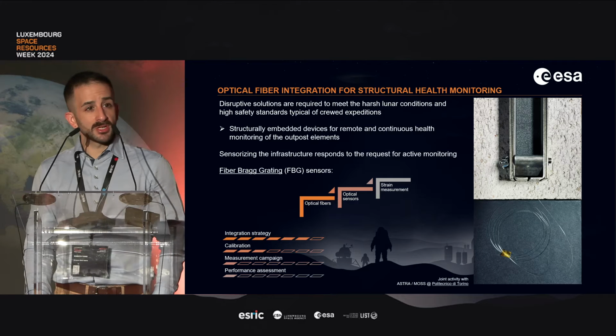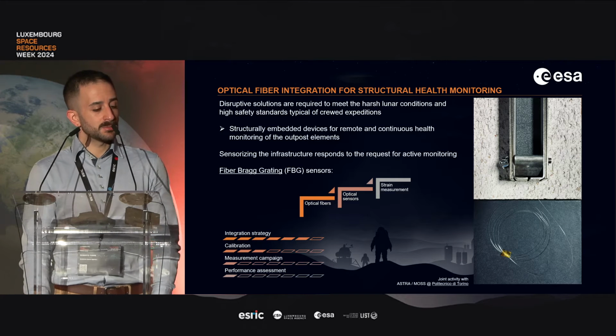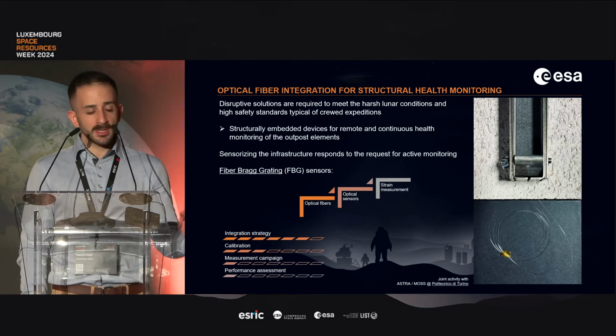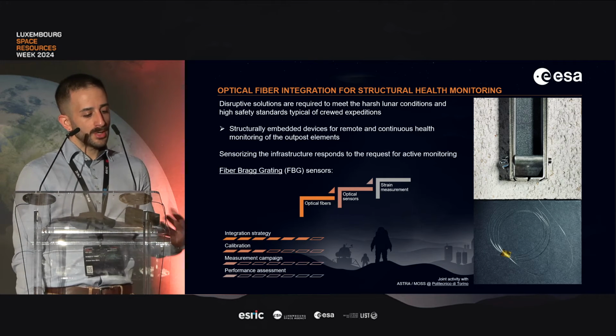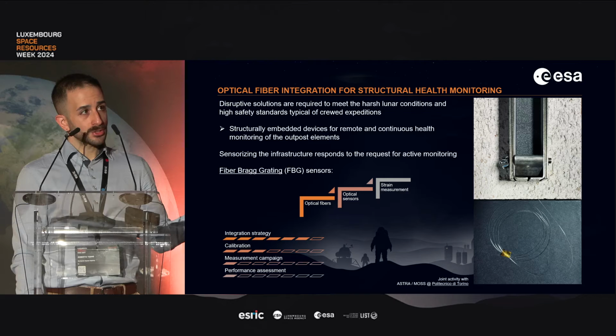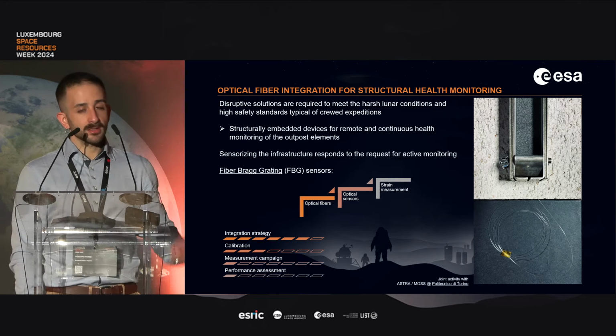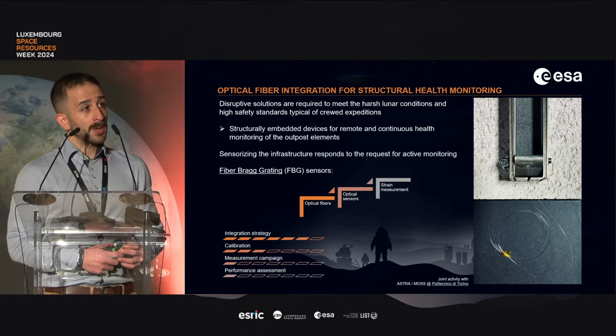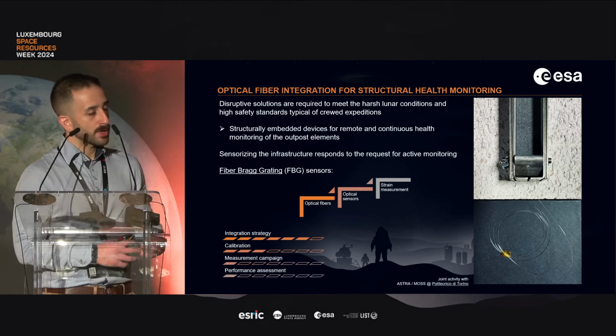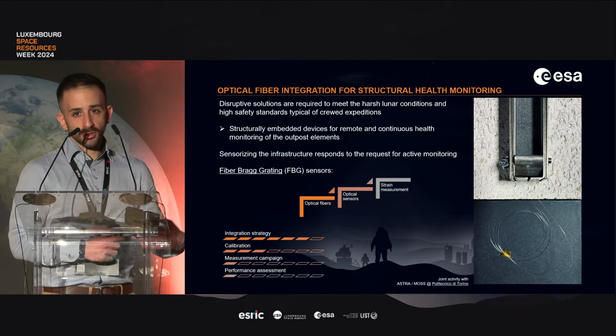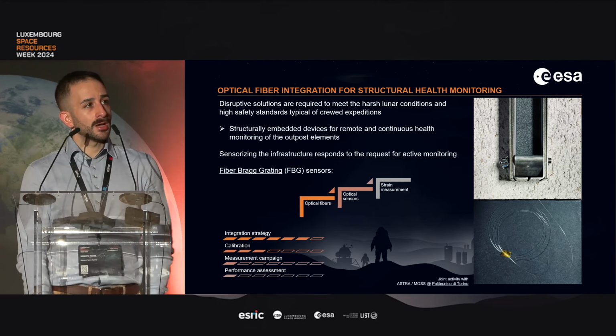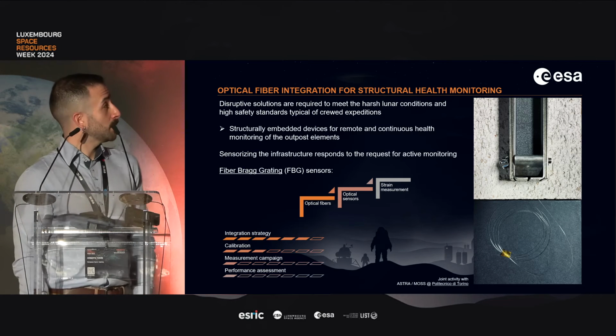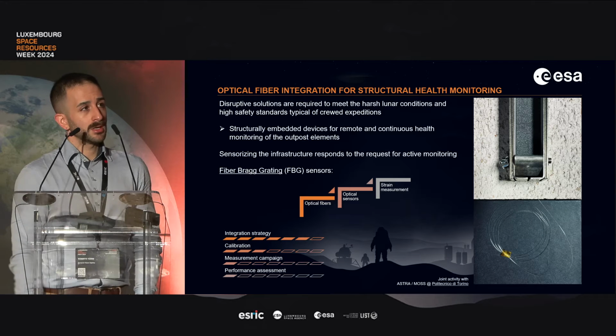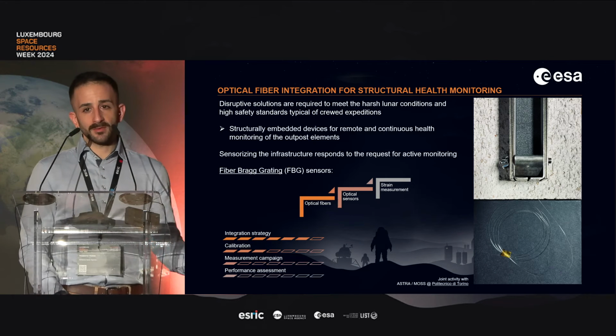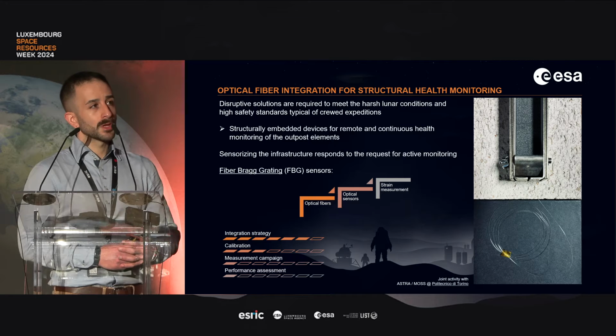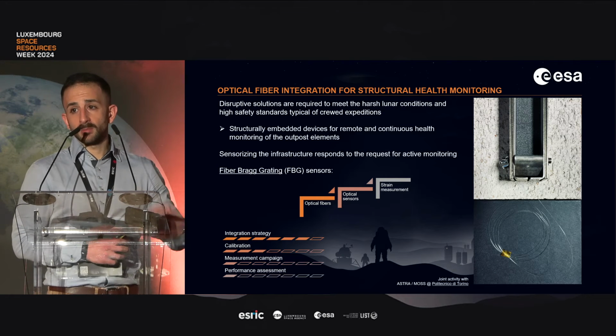Another approach that we have been considering recently is the sensorization of these structural elements. We thought that if we really want to meet the harsh lunar conditions, but also the high safety standards typical of crewed expeditions, we might need some of our structures or some areas of our structures to be actively monitored by a network of sensors. So we thought that optical fibers could be a good solution. You might be familiar with the concept, but you can turn an optical fiber into a sensor by creating a Bragg grating on it, and then you can measure the strain.